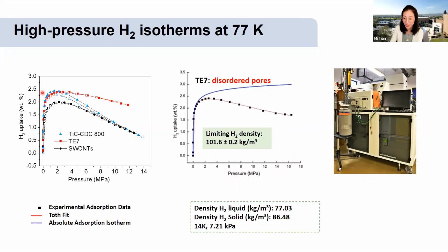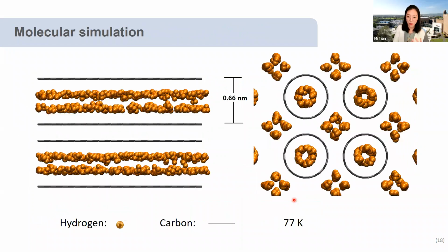It's not surprisingly high, but what surprised us is the hydrogen density calculated from this measurement. The hydrogen density for this activated carbon, for example, is 100 kilograms per cubic meter. And that is even higher than solid hydrogen density. So we really want to know what happened inside. We carried out molecular simulation to visualize what happened inside the pores. The golden spheres are hydrogen atoms, and the gray sticks are carbon atoms. We can see hydrogen in this slit pore shape with a pore size of 0.6.